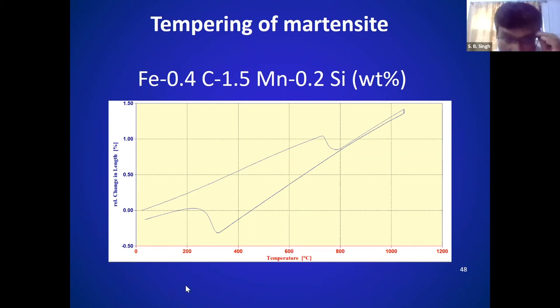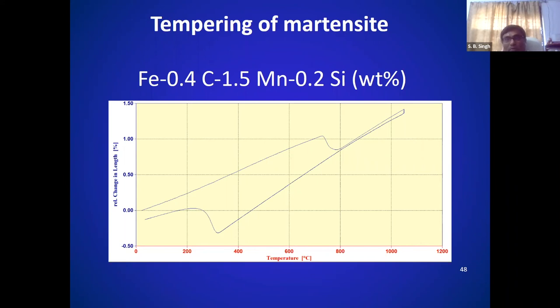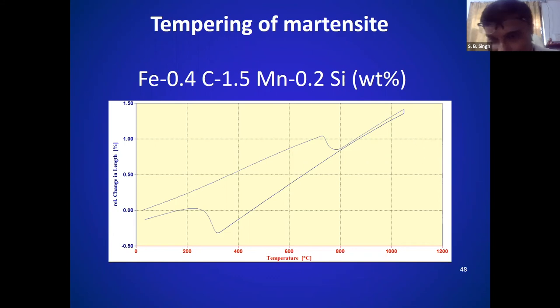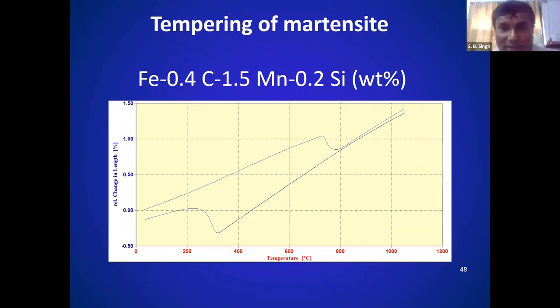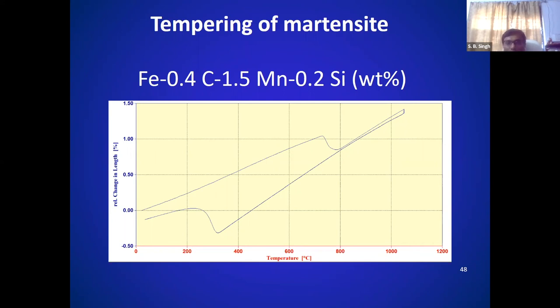Singh: Yes, Harry, that is indeed useful. We cannot look at these results in isolation. For body-centered tetragonal ferrite, we had some results based on transmission electron microscopy, but that community is very rigid — we got results indicating BCT structure matching simulated diffraction patterns, and we argued these can be taken as circumstantial evidence, but the community said it can happen because of a variety of other reasons. We have to see results in totality. Also, somebody pointed out that when martensite forms there are a lot of residual stresses that would affect lattice parameters, but in our case we are using tubular samples with a wall thickness of about two millimeters. Harry: I recommend dilatometry in addition to all the high resolution techniques.